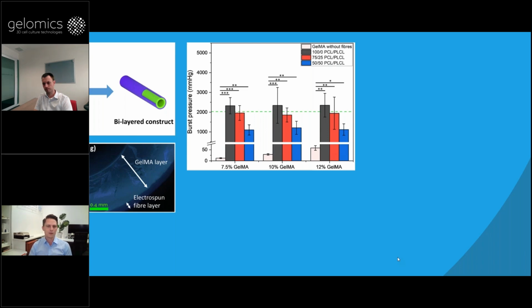In the fiber-reinforced hydrogels, towards the end of our research, we could really tailor the mechanical properties to be very, very similar to actual native tissues as well. And during my PhD, we've also looked at the effects of mechanical loading on the accumulation of these cartilage-specific protein markers, and we found that these have also improved and increased. So for example, collagen type 2 accumulation, when you apply mechanical loading that simulates joint movement, has really improved and increased quite significantly as well. Same with, I believe, mechanical properties and gene expression as well. So that's kind of in a nutshell, but if the person is interested to hear more about it, we've got a few papers that we can share and also share our thoughts.